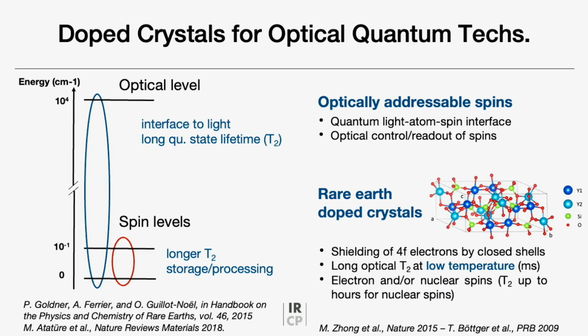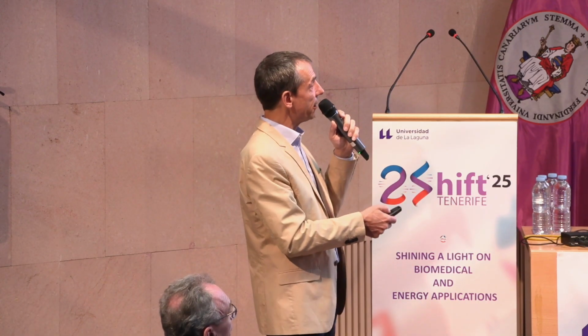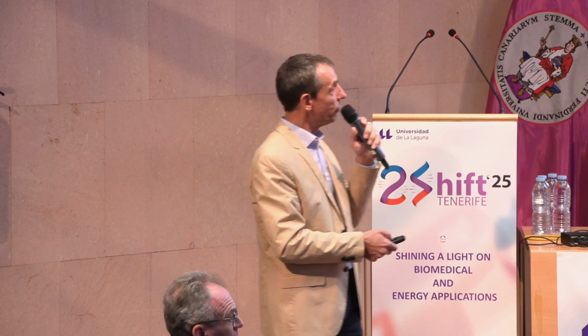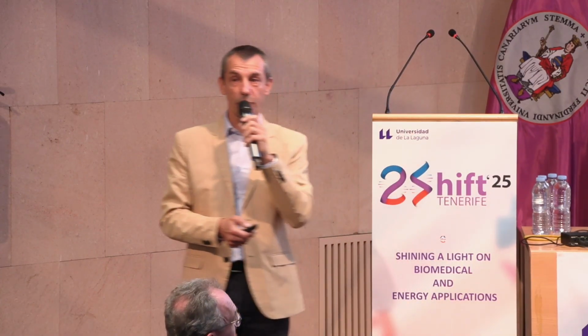As I'm sure many of you know, these elements have this particular property of the shielding of the 4f electrons by closed shells. And this translates into less perturbation from the environment on the optical transitions. And in the end, it's possible with rare earth crystals to observe very long coherence lifetime or quantum state lifetime, so very long T2 in the range up to milliseconds. However, be careful that this is only possible at very low temperatures, so typically below 3K. This is quite unique in the solid state. Rare earth crystals are the material in which you can observe the longest optical quantum state lifetime in any solid.